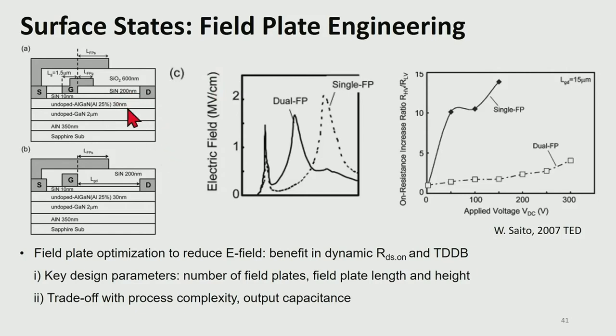For example, instead of using a single field plate, by using multiple field plates, we can effectively reduce the electric field peak. If you see this right figure, compared to the single field plate device, the dual field plate devices show much lower peak electric field, which is also helpful for dynamic RDS,on performance improvement. But the field plate option is not free, because with an increasing number of field plates, the process complexity increases, and it can also affect the switching performance because it increases the output capacitance. So when we design the field plate, multiple factors need to be considered: dielectric TDDB, the dynamic RDS,on, process complexity, and also the output capacitance.